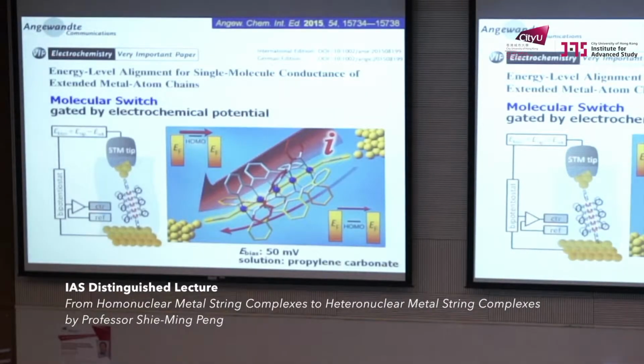Nowadays, we can even apply potential to the two tips. This is the so-called STM break junction methodology. We can apply potential to the two tips. That means we can tune the Fermi level of the electrode. When you tune the Fermi level of the electrode, the conductance will depend on the Fermi level. So before HOMO, you have one state. After HOMO, you have the reduced state. And near the HOMO, we get big tunneling current.